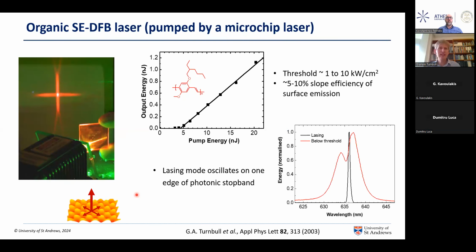So what does an organic laser look like? This is an organic surface emitting distributed feedback laser here. It's based on a two-dimensional feedback grating that's providing the feedback in the plane of the film and a beam emitted out the surface. It has a slope efficiency of, say, typically 10% and a threshold of a few kilowatts per square centimeter. And so it can emit a nice output beam.